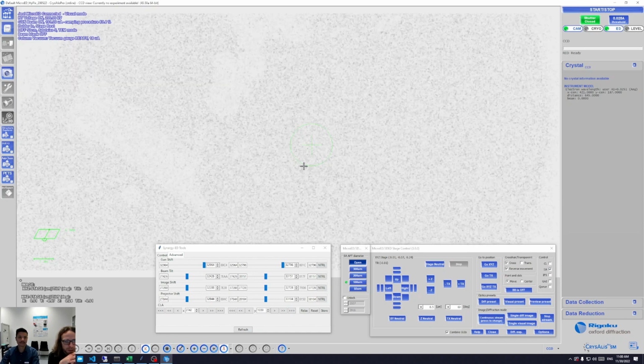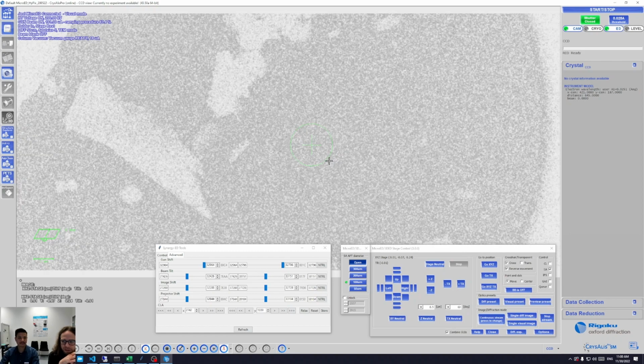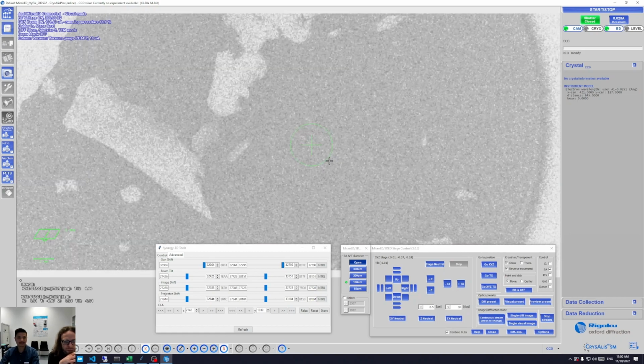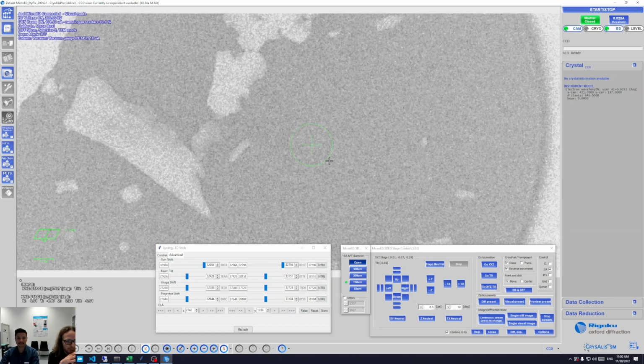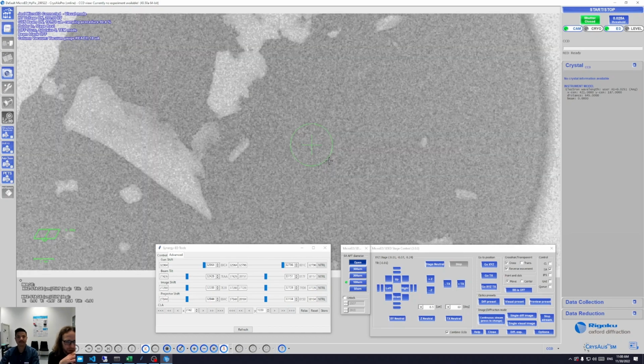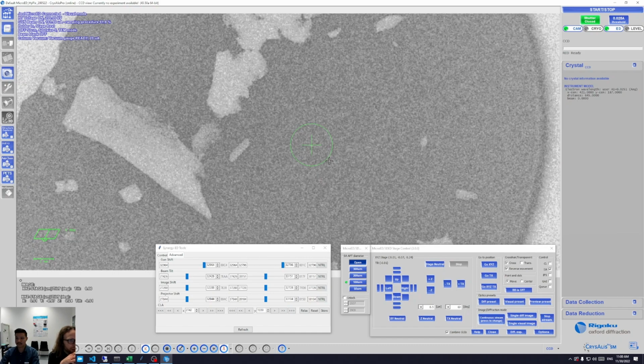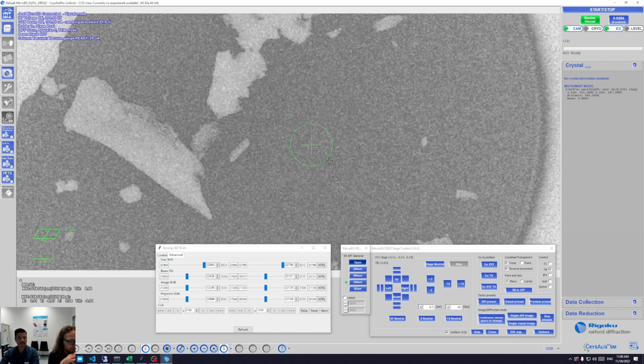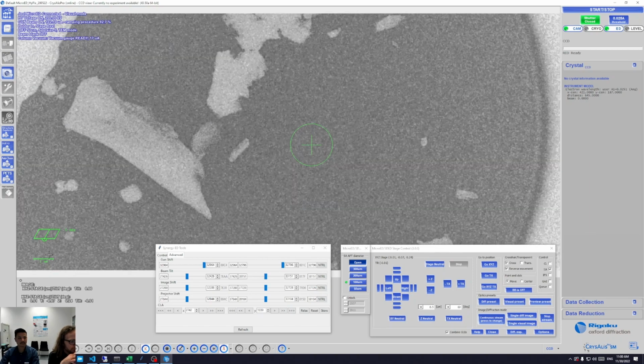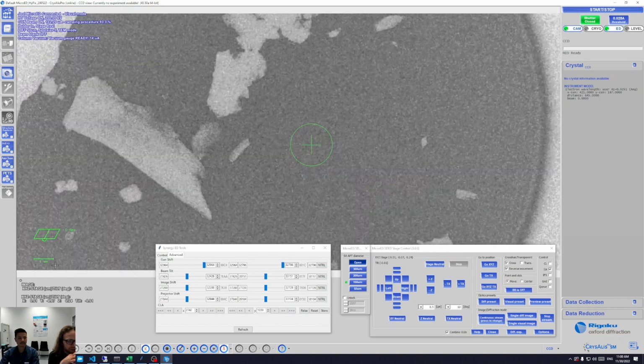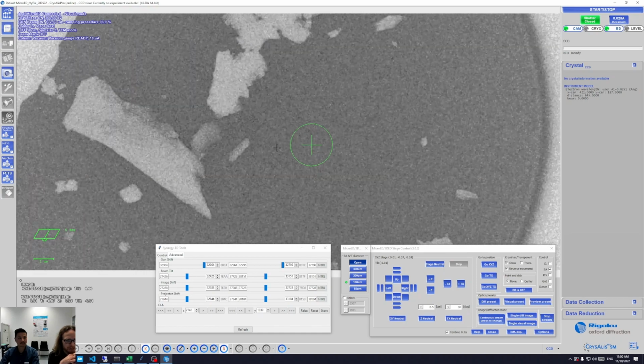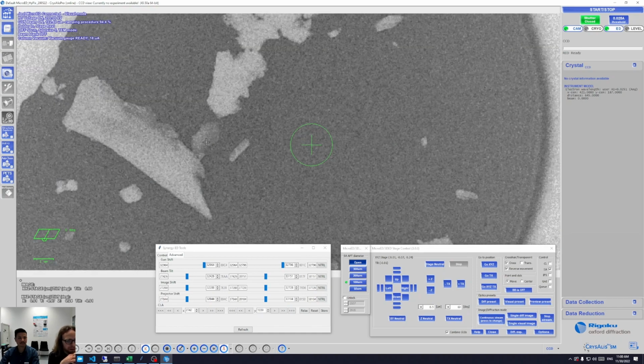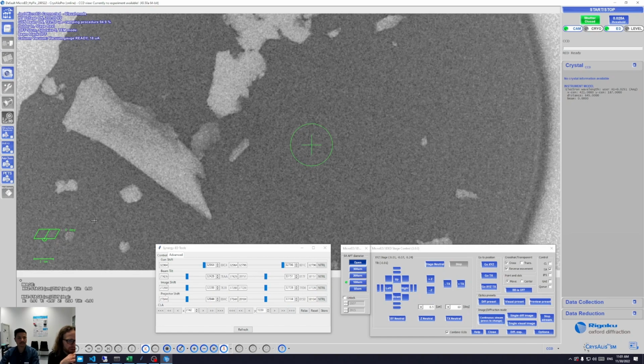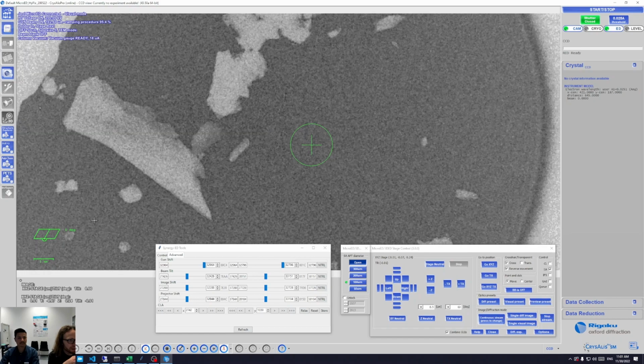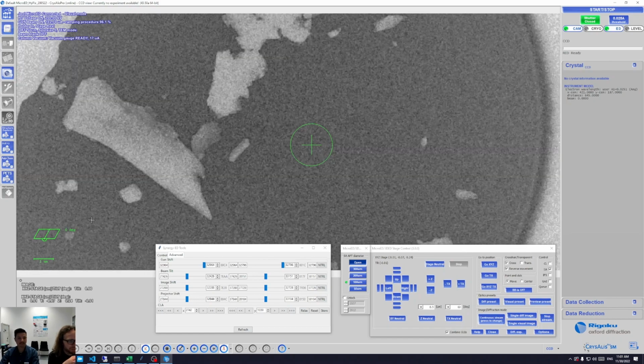And now we should already see, slowly, an image appearing on the screen. We are now in visual mode, which means we have a visual impression of our crystallites. What I can explain already now, while the current is ramping up, is that on the bottom left of this window you see a scale bar. So you see this corresponds to 1 micron, and you can see that those crystallites we have in the field of view already now are in a quite convenient size bracket, and we have a sample that, at least in terms of its morphology, is viable for electron diffraction.